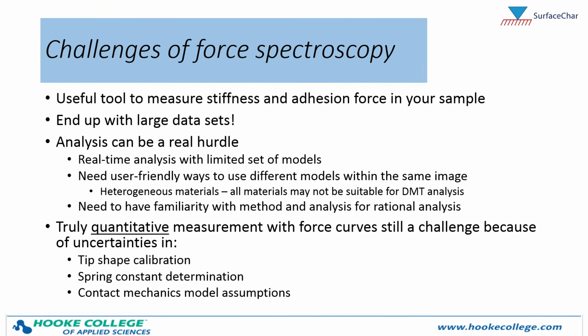Challenges that we still face with this technique. First of all, I do want to emphasize it is a very useful tool to measure the stiffness and adhesion force in your sample. If you do some of this fast force curve acquisition, you do end up with large data sets. If you can imagine having 256 by 256 pixels where each pixel is a force curve, that is a lot of data. So that gets into issues of handling these large data sets. Analysis can still be a real hurdle. So real-time analysis on the fly as you're collecting these force curves is still pretty limited in terms of the models that it can be done with.